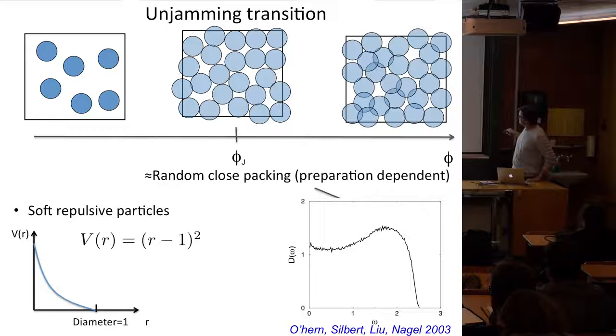The key point is that as you approach this point, all those properties I started to discuss, linear response in those disordered materials, show scaling. So for example, if you go very close to this point and you look at the density of vibrational modes, instead of being quadratic like you would expect from the Debye model, it's actually flat. That means that at very low frequencies, or even at very large length scales, the system never behaves like a continuous elastic solid.